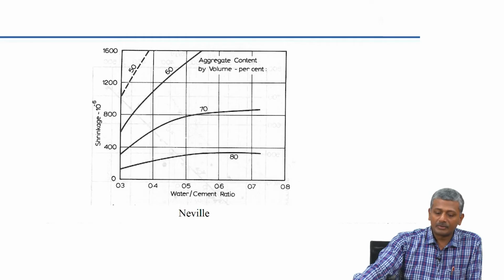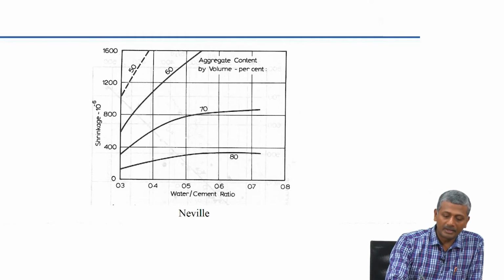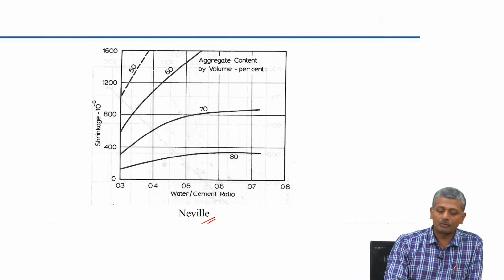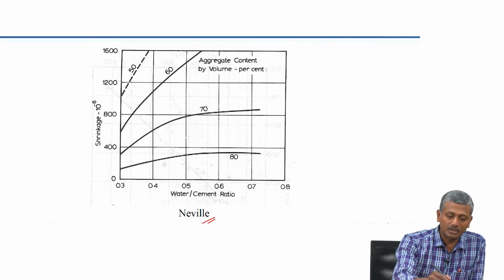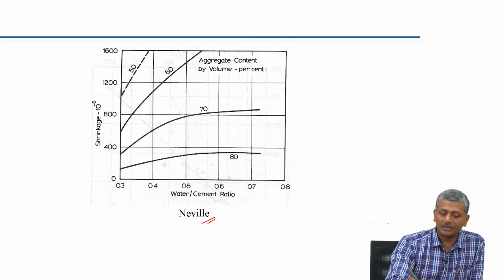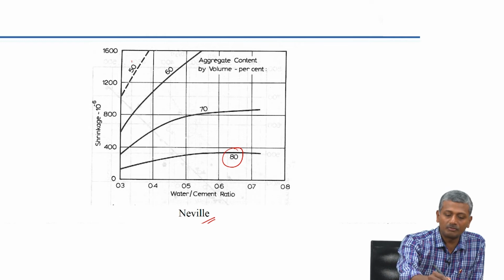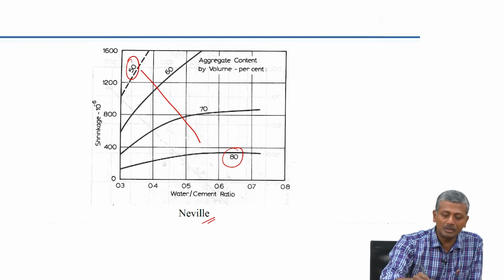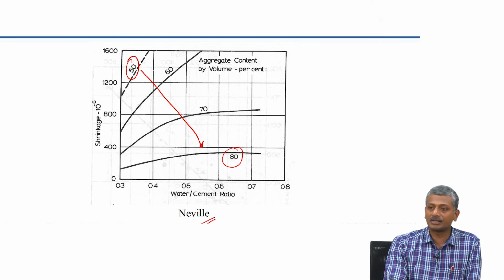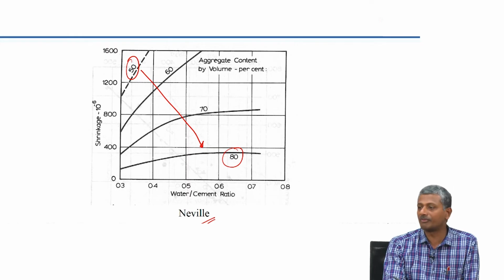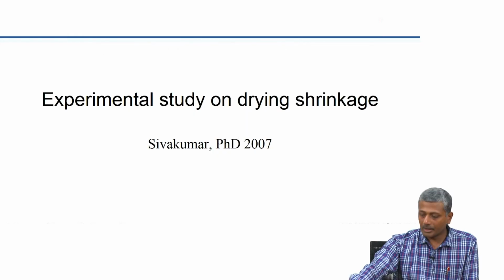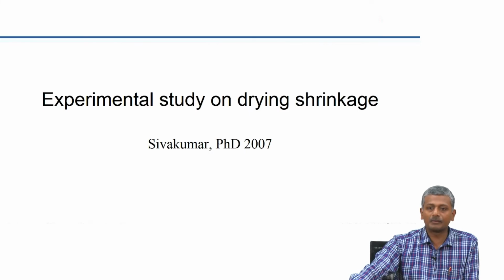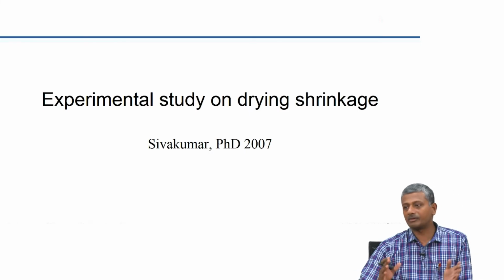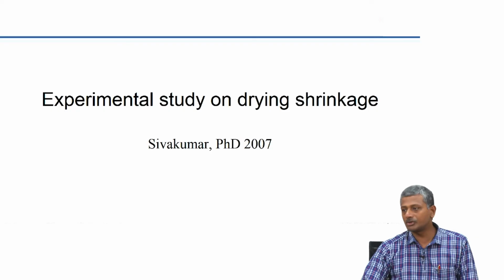Again, these are results from your book by Neville, again talking in terms of water to cement ratio. The extent of shrinkage is being shown here at different levels of aggregate, 80 to 50%. So, when you increase from 50 to 80%, you can see that the shrinkage extent is being brought down by a factor of 4 to 5. That is a significant amount. And again, the same study that I described earlier was also done for drying shrinkage, where we were trying to measure the free shrinkage of prismatic specimens, but there is only so much you can learn from that.